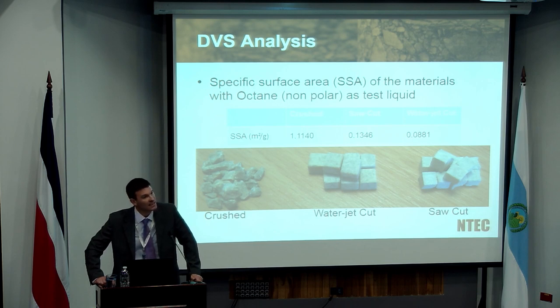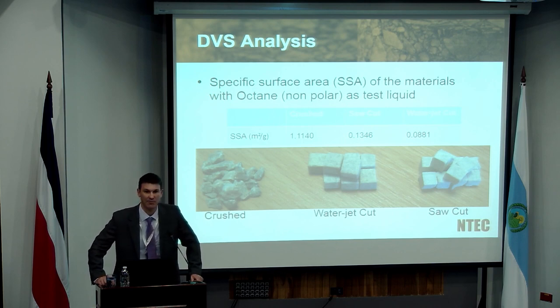Now, is this going to be important for this particular test? Yes. Are we overly concerned? Probably not, because if we're going to do it as a comparative test in terms of adhesion properties for a range of different materials, if we are producing all the materials in the same manner, we are simply fitting up a rating or a ranking system, and therefore, although we're probably not representing the actual adhesion in the material in terms of the asphalt, we are at least able to rank the materials.